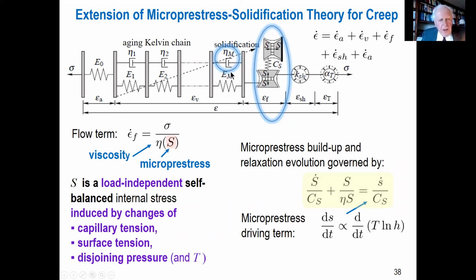Now, all this is controlled by micro-prestress, how quickly it goes. Micro-prestress expresses another fact. It was mainly evident from the so-called Pickett effect, discovered in Wisconsin in 1943, that if concrete humidity is decreased and is constant, specimens creep much less, actually by orders of magnitude. On the other hand, during drying, specimens creep 2, 3, 4 times more than at constant moisture content. So there is some transient effect.